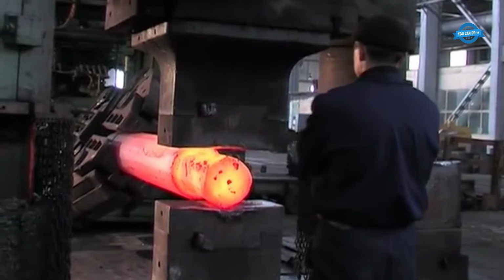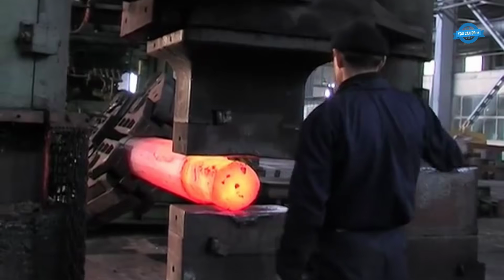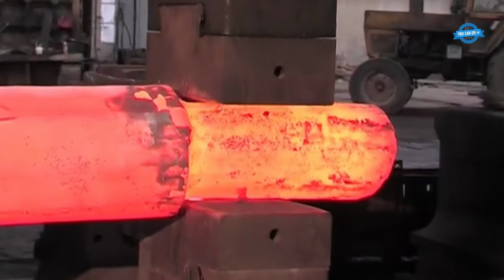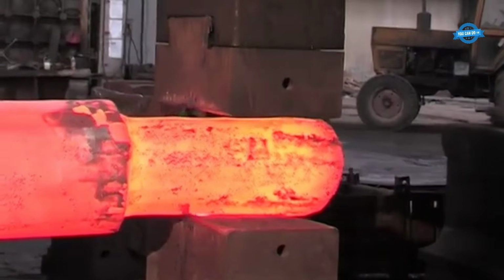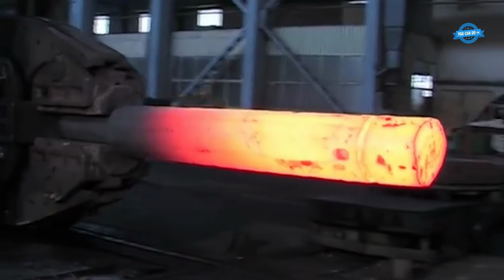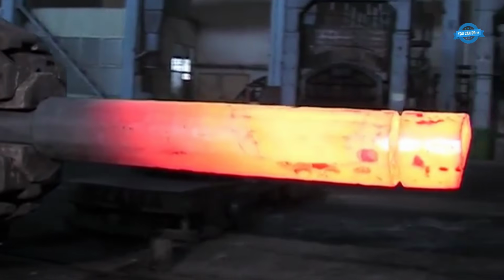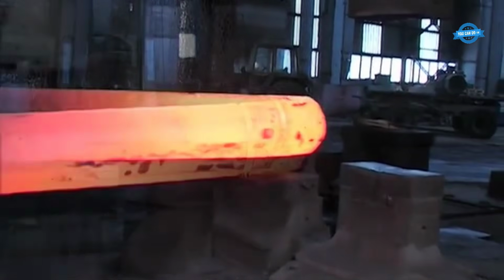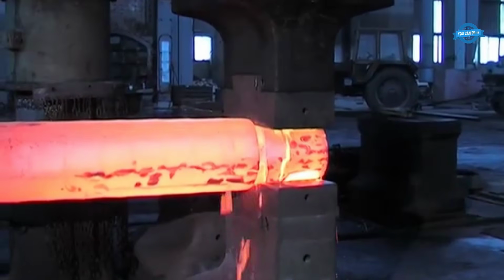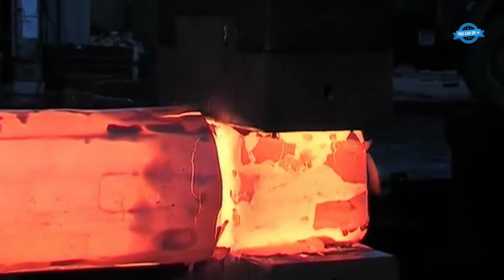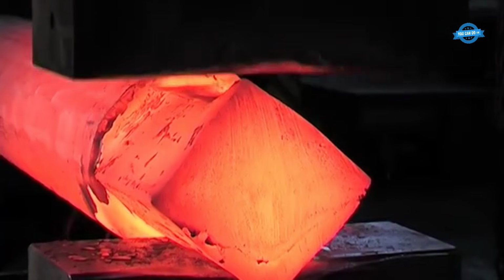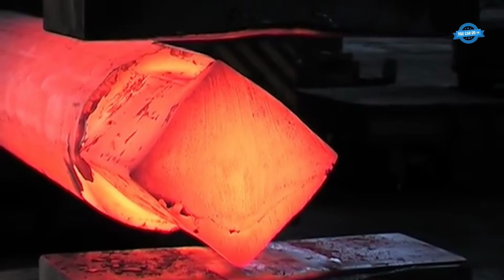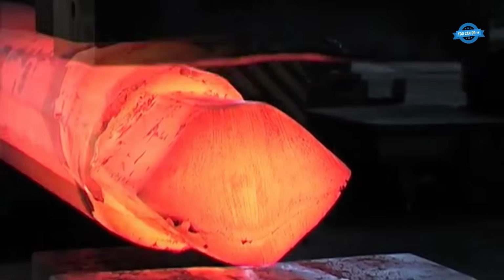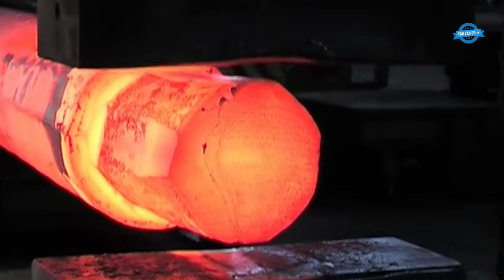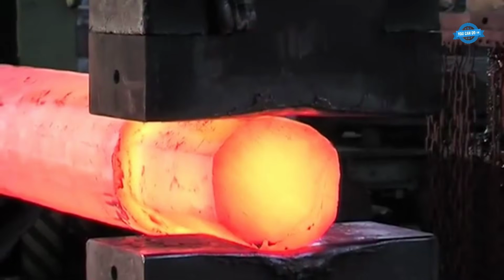The optimization of heating specifications involves careful consideration of temperature and stress fields within the steel ingot during heating. The goal is to achieve rapid and efficient heating while minimizing stress, especially at the core of the ingot. Parameters such as insulation temperature and time during the phase change period are critical for achieving efficient heating. Additionally, the choice between low temperature and high temperature charging methods must be made while controlling the highest charging temperature to prevent adverse effects on the forging.